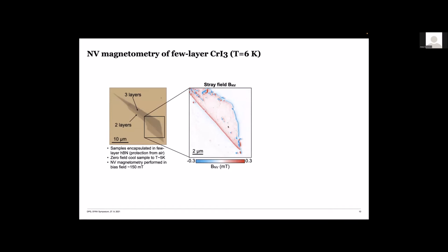And you see right away that these data also confirm this even-odd observation, namely that we see sizable stray magnetic fields emerging from this odd-layer-numbered part, the 3-layer part, whereas there's close to 0 stray magnetic field here on the bilayer. And now again, as discussed already in previous talks, one can in fact reverse propagate these data to the source. One has to make certain assumptions in this, but in the current